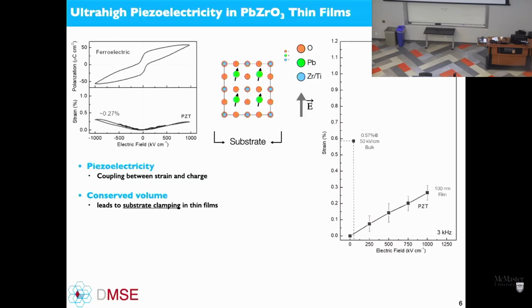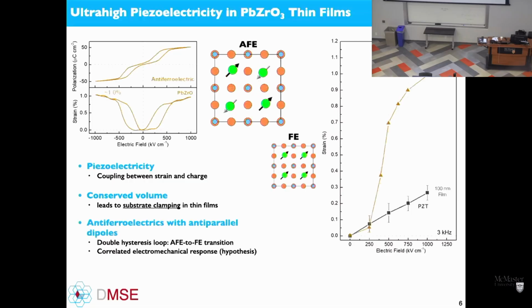But as soon as you grow a thin film, you have to apply a much stronger electric field to get even a third of the strain that you'd get out of the bulk material. That substrate is clamping it and preventing those distortions that would lead to a strong piezoelectric response. So to get a device, you have to go to a very thick film to get the response.